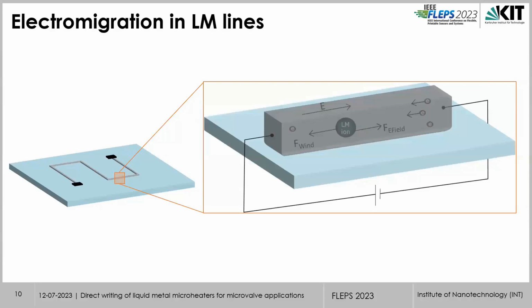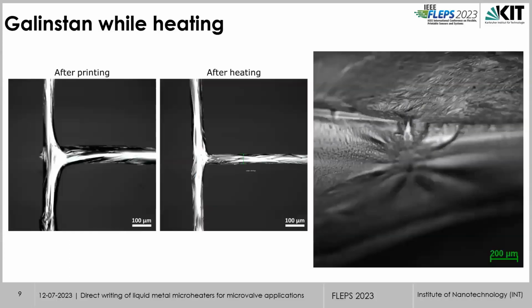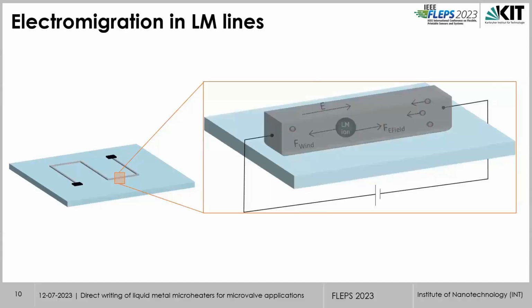So when we apply bias, the electron force generated by the moving electrons on the liquid metal ions is maybe more than the force because of the voltage applied in the electric field. And these liquid metal ions move to the electrode side, and then we have just the oxide layer standing like this. In this case, the liquid metal moves to the sides and the oxide layer remains, which makes it highly resistive, sometimes causing failure of the circuit.